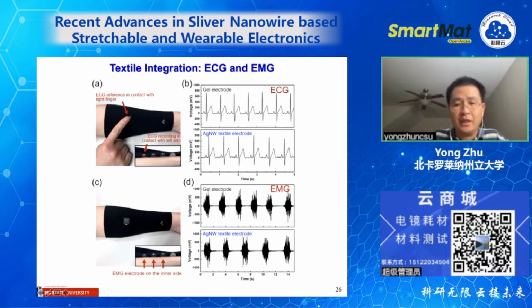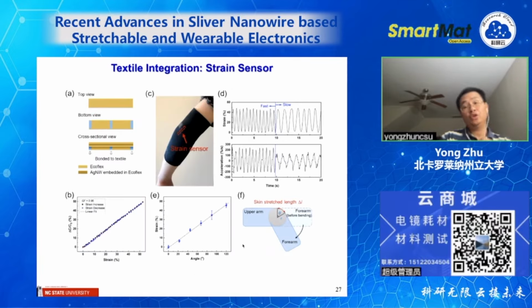And then here we have an EMG electrode. This is electromyography, to measure muscle activity. When the muscle contracts, it generates electricity, generates voltages. So we can measure this, again with a commercial electrode and our electrode, very much comparable. And also strain sensors. With this sensor, we can put it on a joint like the elbow. You can see we can capture the strains at either fast or slow motions.